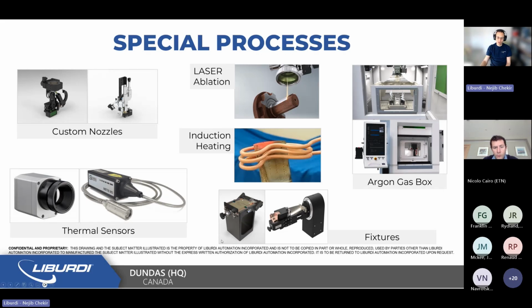And in this case, you can see, for instance, at the bottom, some of the solutions we provide in terms of fixtures for high pressure compressor blades, so HPC blades, blade tip repair can be used as well for the leading edge repair, in rare cases trailing edge as well, or for the LPT blades. So in this case, you can see a fixture that's focusing only on the Z-notch and the shrouds perimeter areas. But you can also include the seals at the top as well.